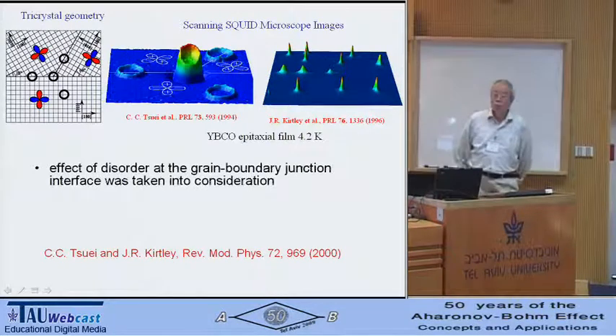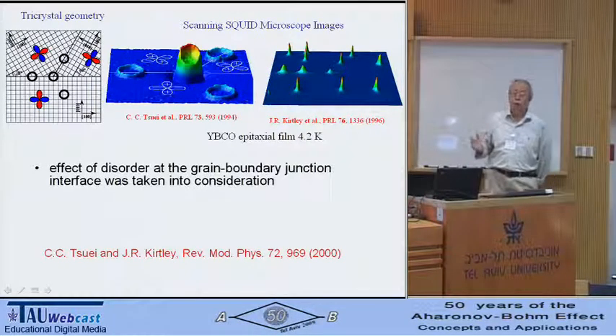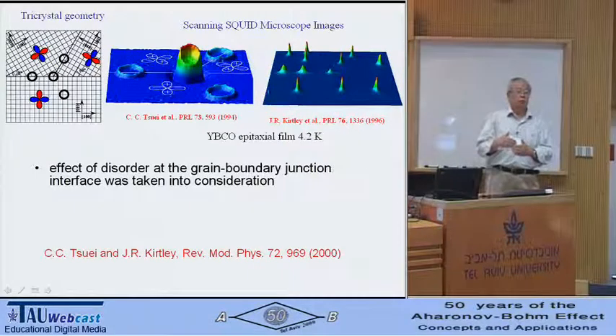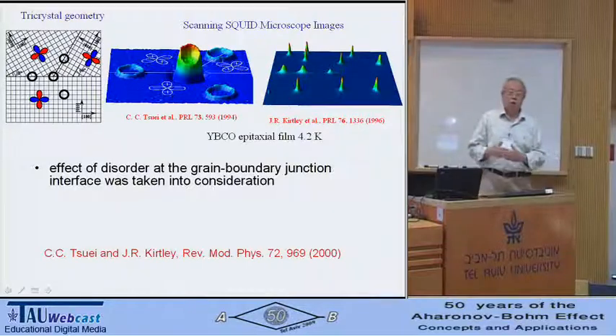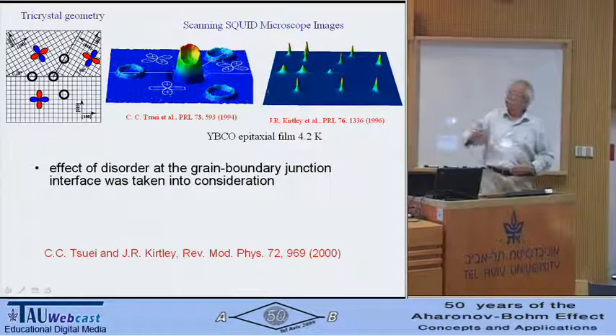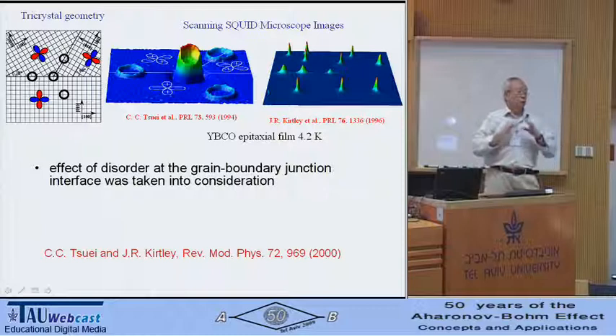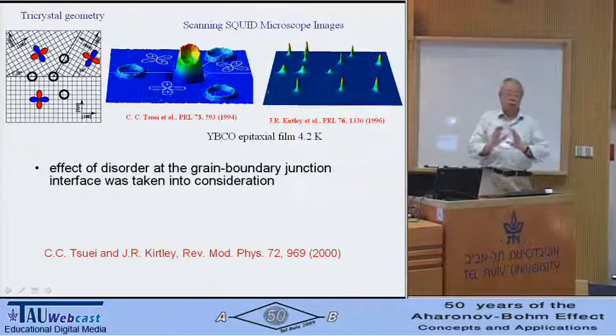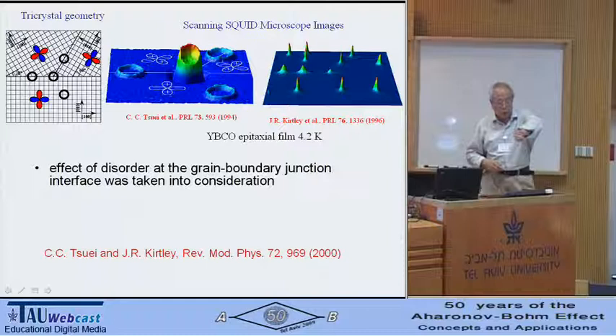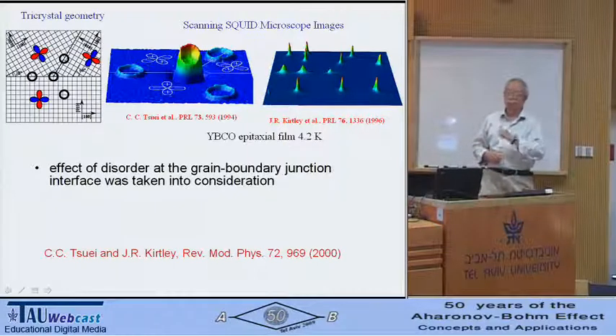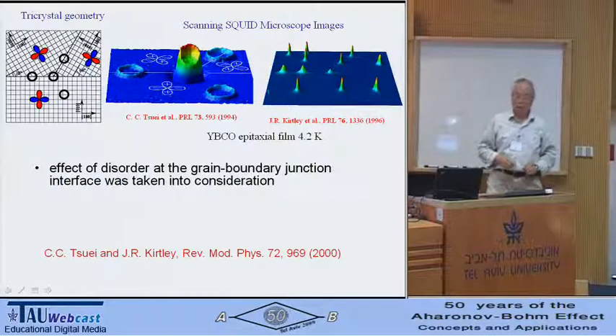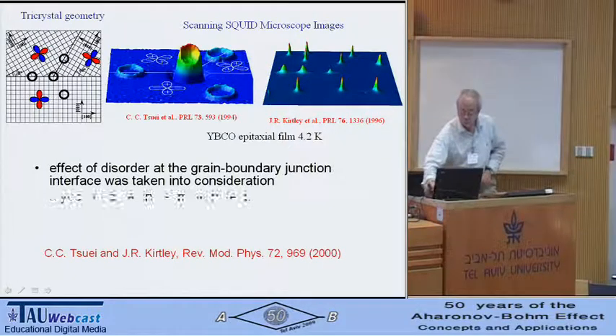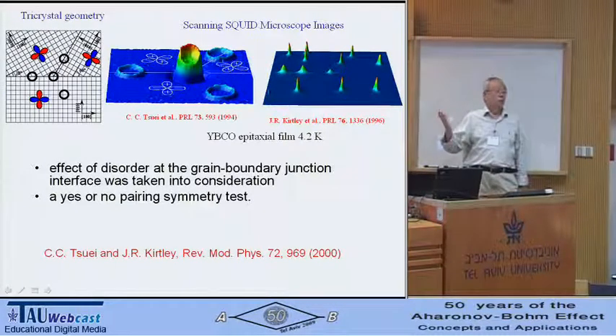Now I want to mention that when I designed this experiment, I took into account that the grain boundary junction interface may not be ideal. So I used the formula of Sigrist and Rice for the clean limit as well as the formula I developed for maximum disorder. So in other words, this design is foolproof. Regardless of how bad the junction interface is, as long as you have a supercurrent flowing, you will get a half flux quantum if it's a d-wave. So this really is a yes or no pair symmetry test.